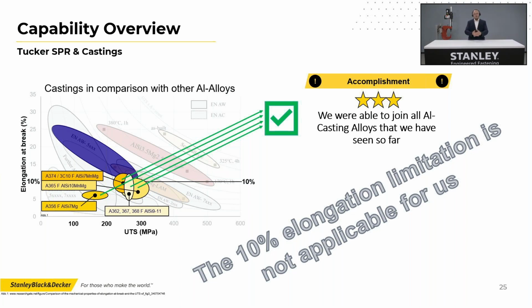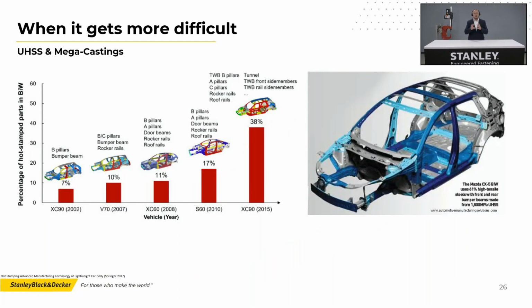But what happens when it gets even more challenging? We have talked about the casting, so the bottom material and the deformation of it and the cracks and all the challenges that come with the casting. But now let's talk a little bit about the joining partner. What happens if the joining partner is an ultra high strength steel, 1500 megapascal, 2 millimeters, or 1800 megapascal or 2000 megapascal? And we see this trend going up that the use of these steels increases, but of course you have to have a solution to join them, because a 2000 megapascal with mechanical joining, that's quite difficult, right?